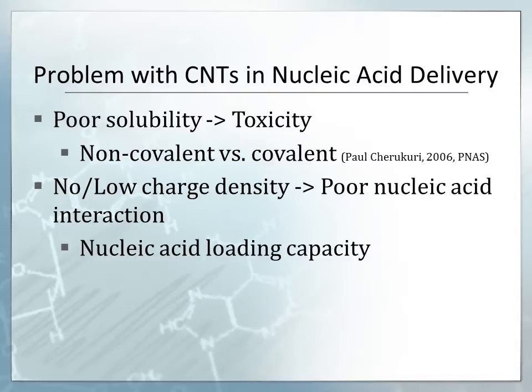Also, nanotubes don't bind to nucleic acids spontaneously because they don't bear any charges. Even the naturally occurring carboxylic acid on the nanotubes, if you functionalize or purify them with an acid, for example, the charge density is very low. So they do not interact with the nucleic acid effectively, and therefore the nucleic acid loading capacity is very low.